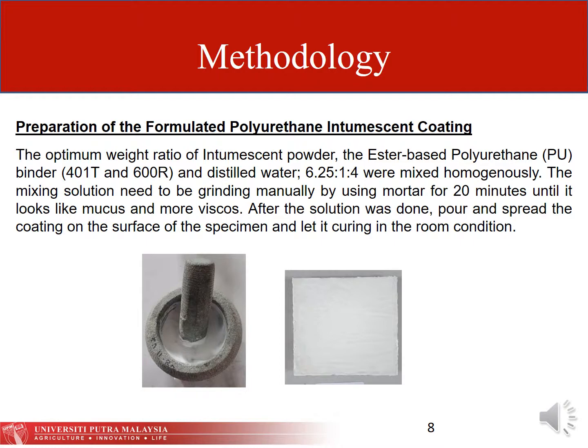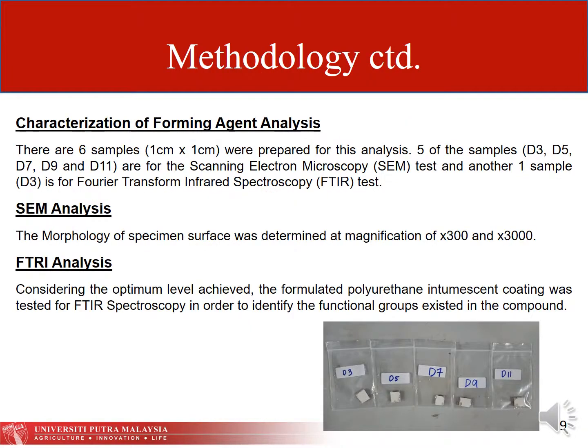After the solution was done, pour and spread the coating on the surface of the specimen and let it cure in room conditions. For characterization of the forming agent analysis, 6 samples were prepared. 5 samples are for the scanning electron microscopy test and another 1 sample is for Fourier transform infrared spectroscopy. The morphology of the specimen surface was determined at magnifications of 300 and 3000 in SEM analysis. For FTIR analysis, considering the optimal level achieved, the formulated polyurethane intumescent coating was tested for FTIR spectroscopy in order to identify the functional groups existing in the compound.